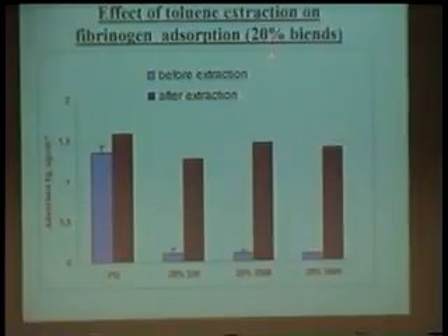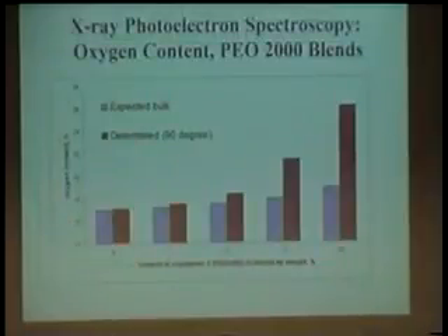If you do this on those blended materials with the 550, 2000, and 5000 material, you find that the low protein adsorption before extraction shoots up dramatically and recovers back to the value that you had before you blended this PEO component in. So there's no doubt that the toluene extraction is removing the PEO component.